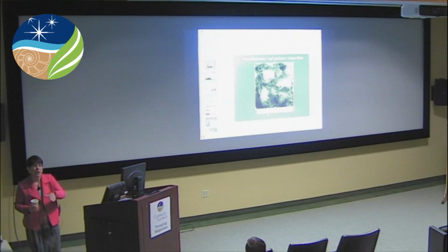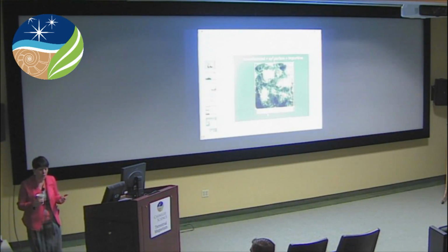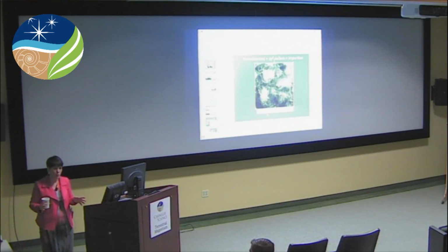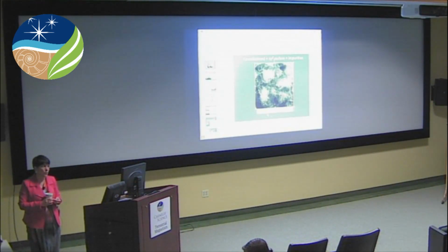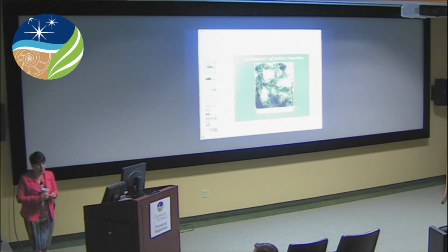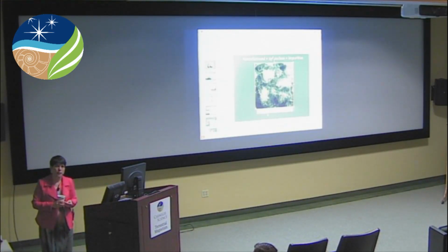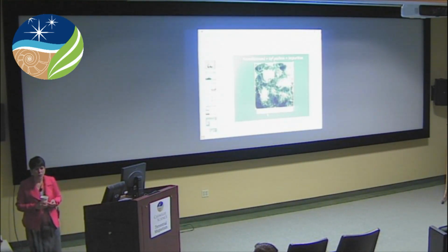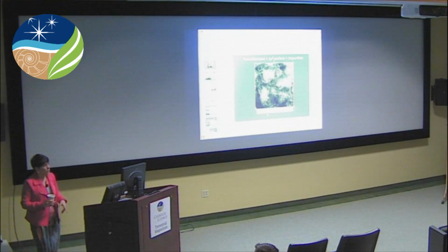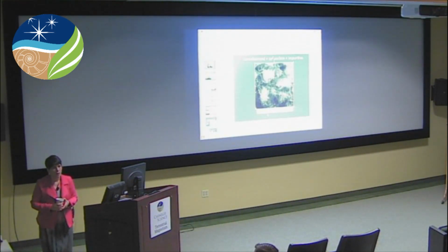Okay. So those are very nice images. My question is, besides impurities, if you have a vacancy, can you look at that as well, or is it not possible? It depends. In principle, yes. You may or may not be able to image a vacancy directly. It used to be totally impossible, and now it is possible depending on the geometry of the sample. If you have perfectly flat faces, so there's no height variation, no dimples or hillocks in the sample, then the image intensity contrast can be directly interpreted. Where you see a dark spot, there has to be a vacancy. That turns out in practice to be very hard to achieve, and that would mean you were also working with a very thin sample of only one element.